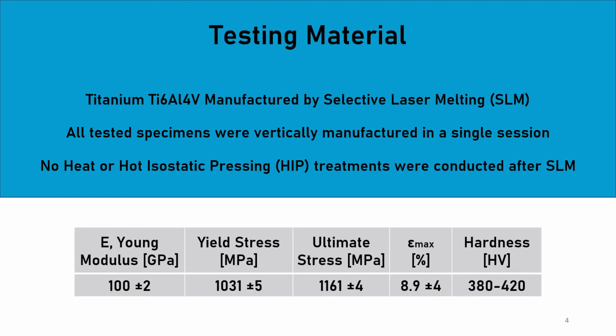Now, the material applied to the ultrasonic fatigue testing machines is the titanium Ti6Al4V. All specimens were manufactured by the selective laser melting method. They were manufactured in one single session vertically. Both ultrasonic specimens and basic mechanical property specimens were manufactured in the same section. No heat or hot isostatic pressing treatments of any kind were applied to the specimens after the selective laser melting method. And here we obtained basic static mechanical properties of the titanium tested in this study.